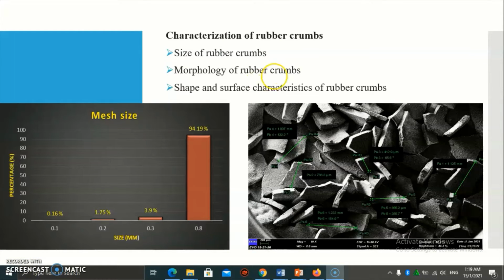For the next part I will explain the characterization of rubber crumbs: size of rubber crumbs, morphology of rubber crumbs, and shape and surface characteristics of rubber crumb. This data shows the size of rubber crumbs. The mesh sizes of the sieve used in this process were 0.1 mm, 0.2 mm, 0.3 mm, and 0.8 mm. Crumbs with diameters of 0.8 mm, 0.3 mm, 0.2 mm, and 0.1 mm were physically characterized. The largest one is 0.8 mm, so this is the crumb size we use for making the composite.